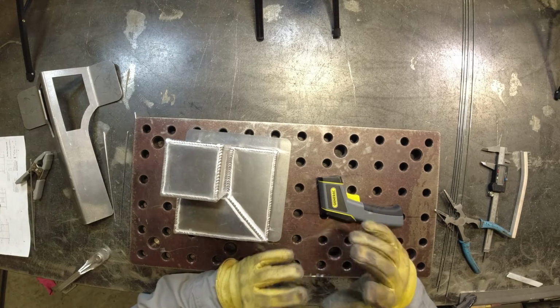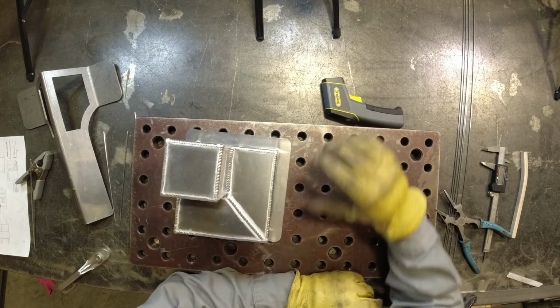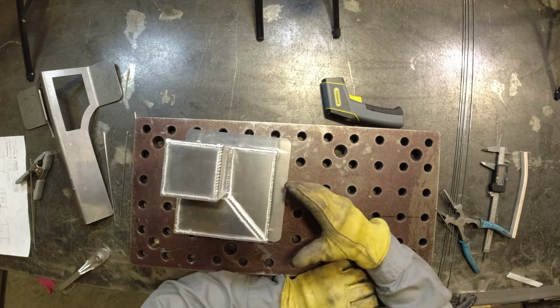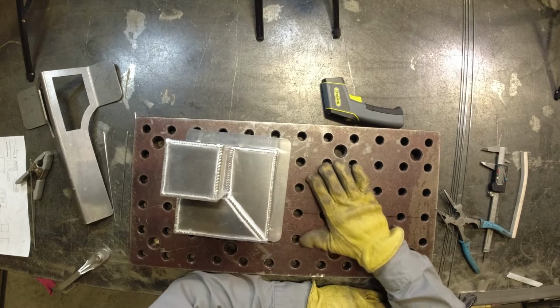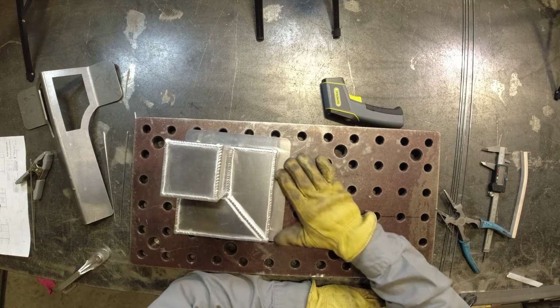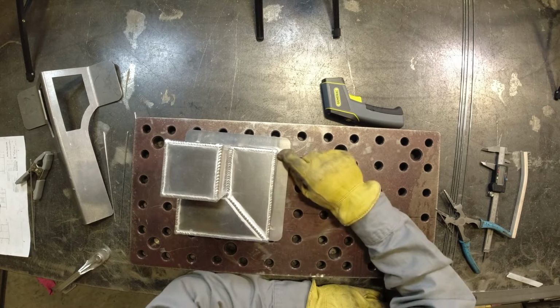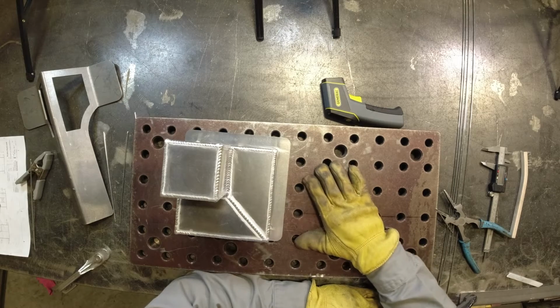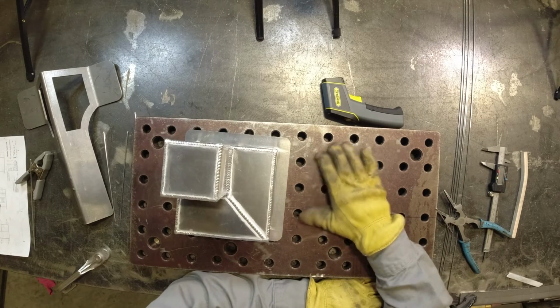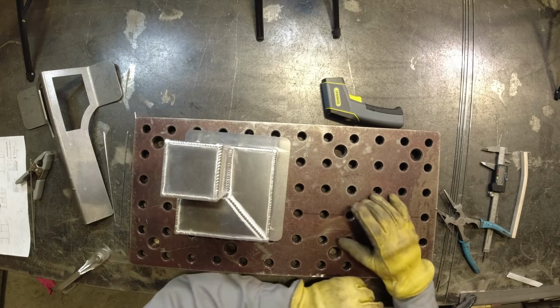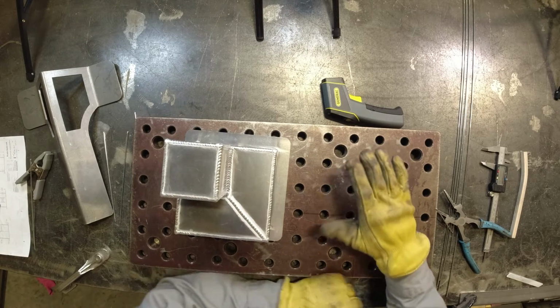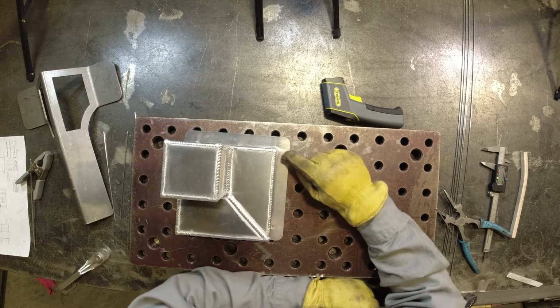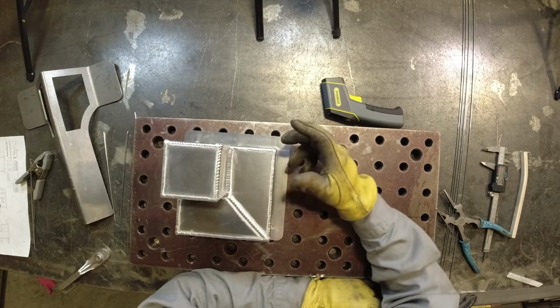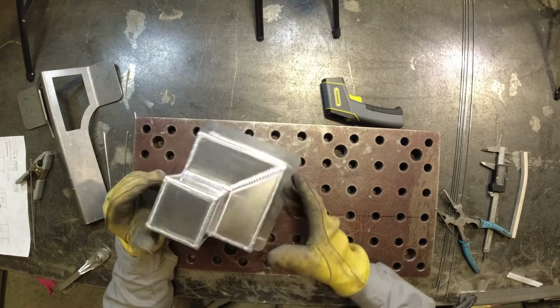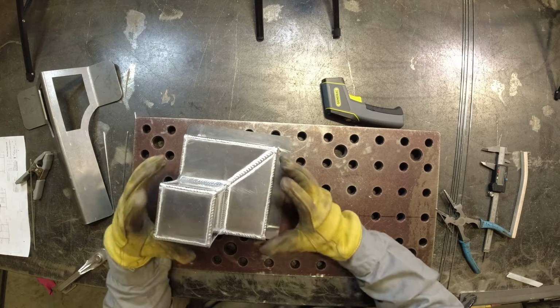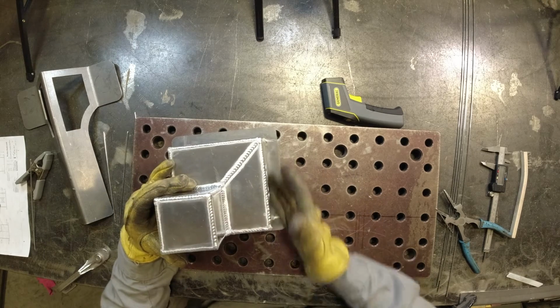And the hidden secret to a lot of reasons why people struggle with a fillet weld in the flat position is that they have a nice thick workbench underneath, sucking the heat out of it as fast as they can put it in. So if you're welding a fillet weld on top of a surface, especially if you have a heat sink plate that's aluminum, I've seen a lot of people have 2-inch thick aluminum heat sinks on their workbench, this weld joint is naturally going to need 50 more amps than this top corner joint. And so the reason why we welded that last is because we wanted the overall temperature of this project to be higher to help us soak in this bottom fillet weld.